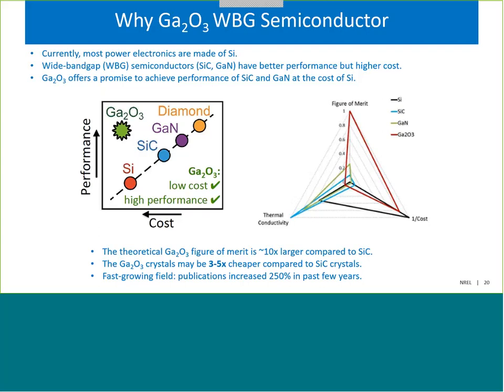The spider chart below compares the performance of gallium oxide with that of silicon, silicon carbide, and gallium nitride. And as you can see, gallium oxide has the highest figure of merit. It has a low cost, but one of its drawbacks is its thermal conductivity, which is relatively low.